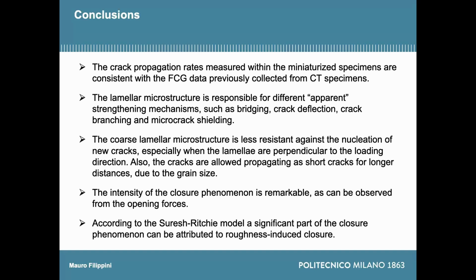So my conclusion up to now is that the crack propagation rates that we measured with this miniaturized or sub-sized specimen are consistent with the fatigue crack growth data that we previously collected on CT specimen. The lamella microstructure is responsible for an apparent strengthening mechanism that is bridging, crack deflection, crack branching, micro crack shielding, all together. So it's very difficult to separate the single effects.